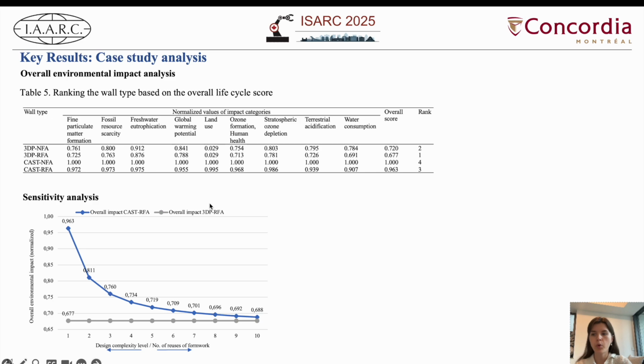Our sensitivity analysis focused on the reusability of plywood formwork in the casting process. While materials like sodium hydroxide and steel cannot easily be reduced without compromising strength, formwork can potentially be reused, depending on the quality of the material and the complexity of the building design. The results show that reusing formwork even once can significantly lower environmental impact. However, when we use it 10 times, for example, the overall impact of casting still remains higher than 3D printing, which requires no formwork at all.